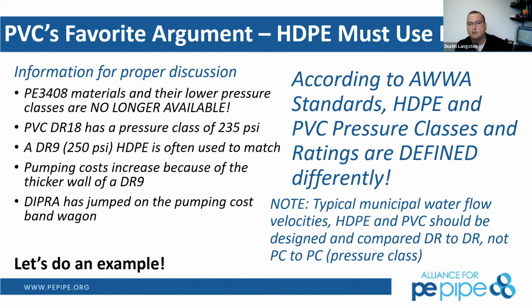So PVC's favorite argument is, hey, if you use polyethylene pipe against PVC, you need to have 2 things. You need to have the same inside diameter. You need to have the same pressure class. And so what that forces us to do is, if they go out and say, hey, we've got a DR18 here, rated at 235 PSI static pressure rating, you have to use a DR9 polyethylene with 250 PSI pressure rating. And that forces us to go up another diameter to get the same inside diameter as the PVC original design. And this is absolutely not the case.